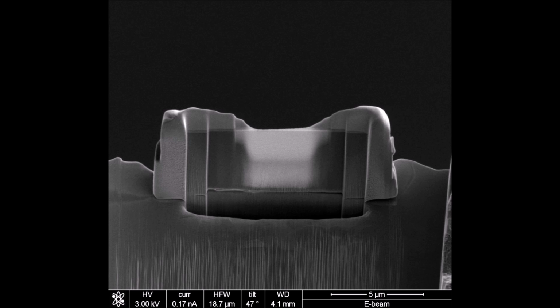The other main consideration when you're making the lamella is what information are you trying to get from it when you then go and perform TEM on the lamella. And obviously you want to think this through and figure it out before you get to the FIB, because what you do in the FIB is definitely dictated by what the end information you're trying to get in the TEM is supposed to be.